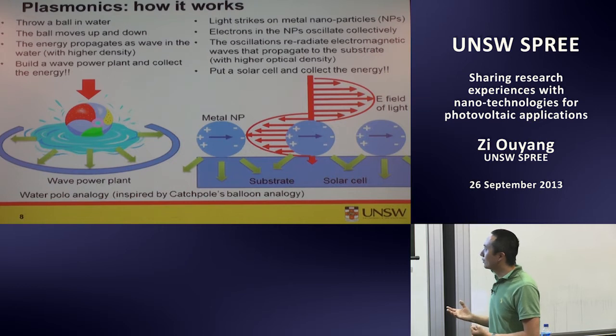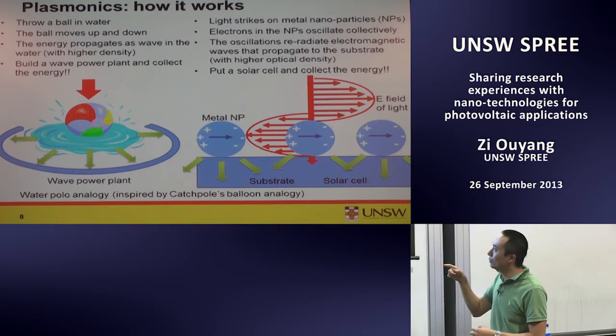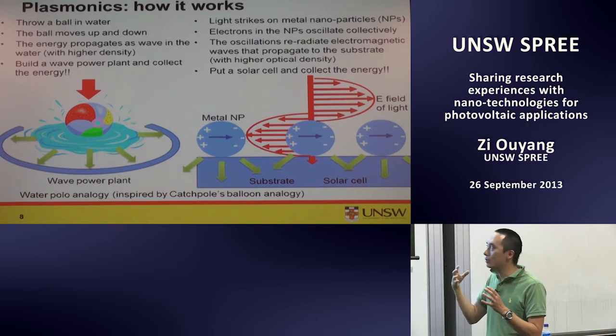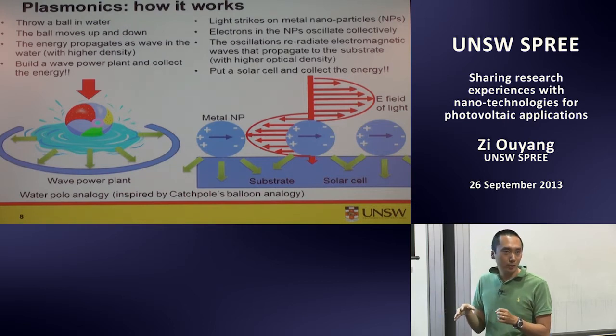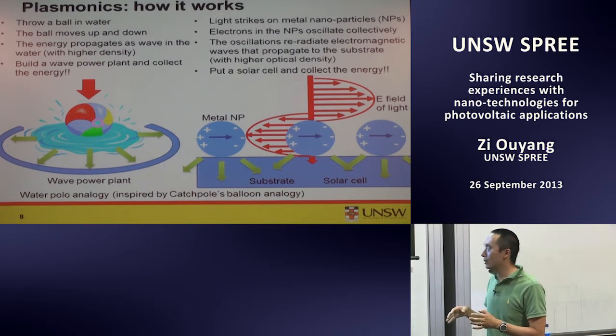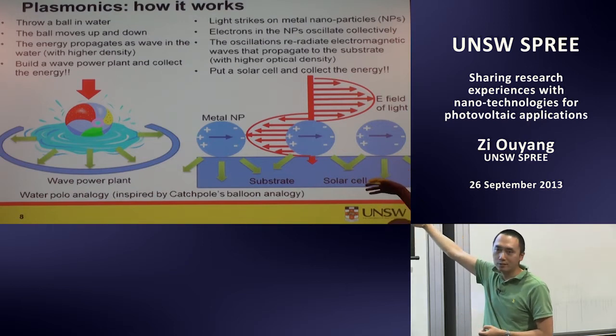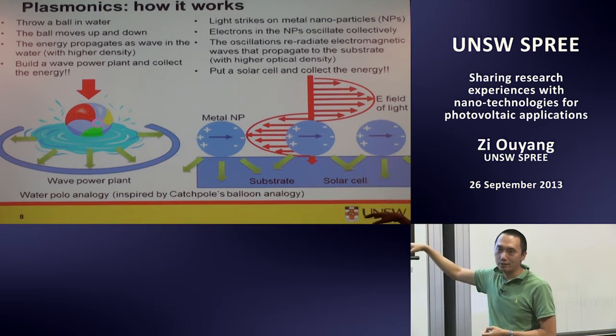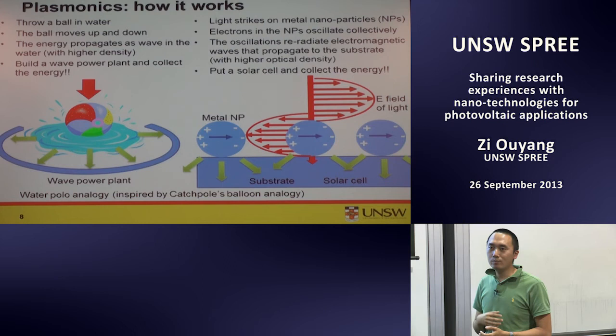And also on the left-hand side, the energy will not go much to the air, because the density of the air is too small compared to the water. So most of the energy will go to the high density material, which is water in this case. And on the right-hand side is a high refractive index material, which is a substrate. So you have a significant forward scattering effect on the right-hand side, which when we make solar cells, we like, because we call it the anti-reflection effect.